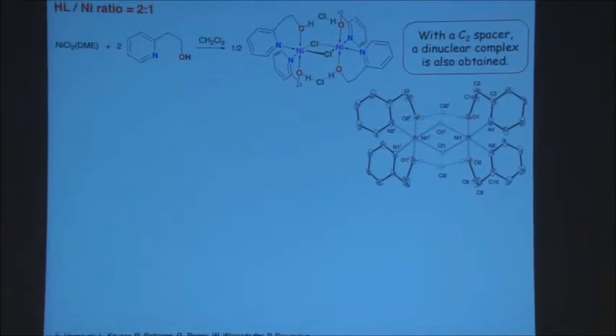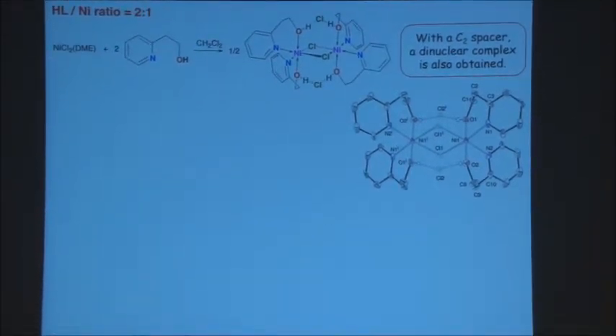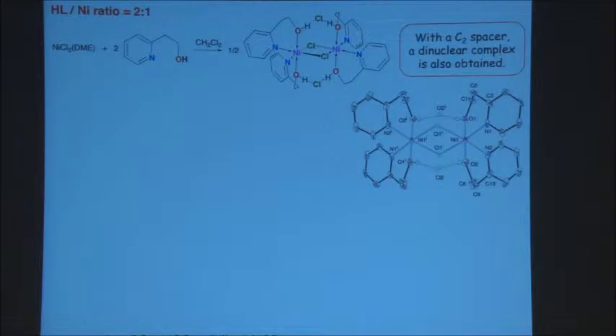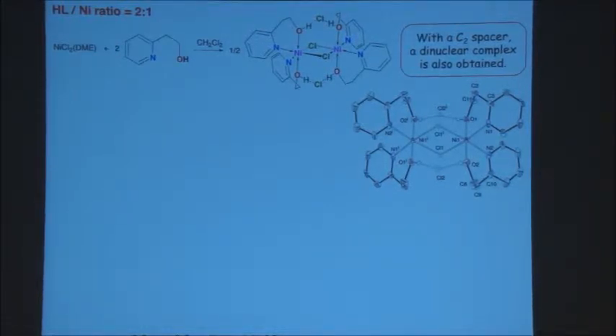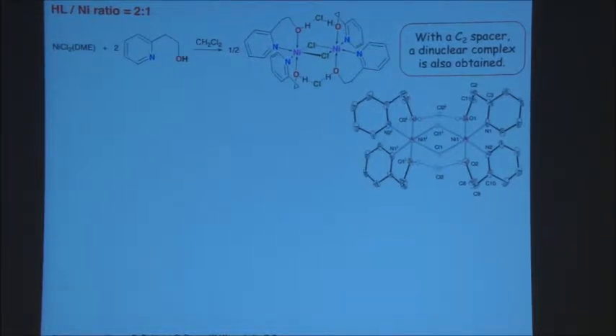What about the C2 spacer, the longer chain here? We now react the same ligand with a nickel precursor. DME is dimethoxyethane, which is a very labile chelating ether, easily displaced by an entering ligand. So you have a very nice precursor which can be used in a controlled manner. If you react these two in dichloromethane, you form again a dinuclear structure that was again established by X-ray diffraction. Again, you see that the counter-ion here, the chloride, is interacting with the alcohol function by hydrogen bonding. And we will see that it is not totally innocent.